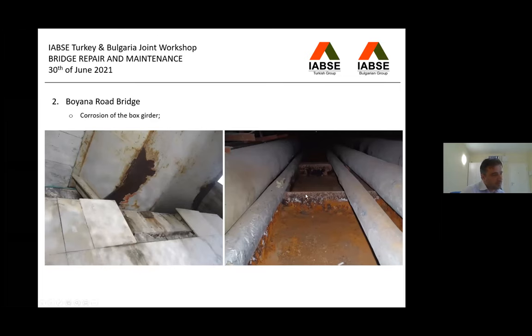The corrosion inside the box, on the bottom plate, is also uniform corrosion over the first fields. But I have to mention that the water inside the box was not coming through the concrete plate, but mainly through leakage of the expansion joints. Due to the longitudinal slope of the structure, it goes from field to field. The first fields next to the bearings were the most corroded.